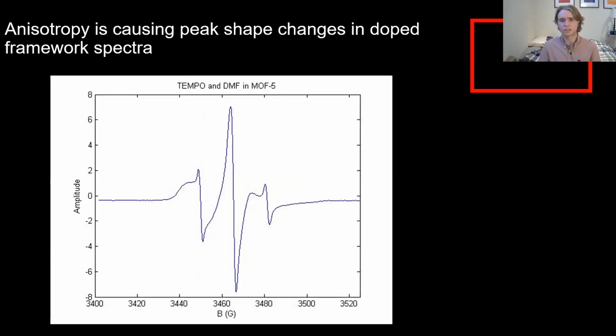Now, another thing that was maybe causing some problem with the quantitative data collection, but is pretty interesting to think about, is something called anisotropy. As we can see in this spectra below, that middle peak is still pretty sharp and normal looking, but the 2 peaks on the sides are quite different. They have a very, very different character to them. That's caused by anisotropy, which isn't something we can just inherently remove. It's just a natural part of the system, but it does make quantitative data collection perhaps a little bit more